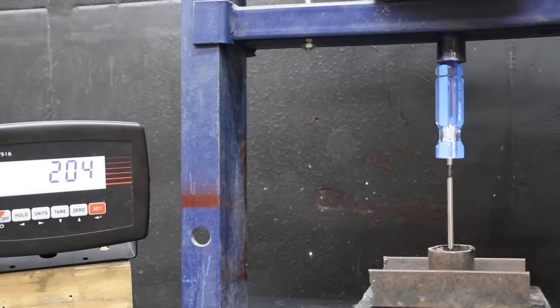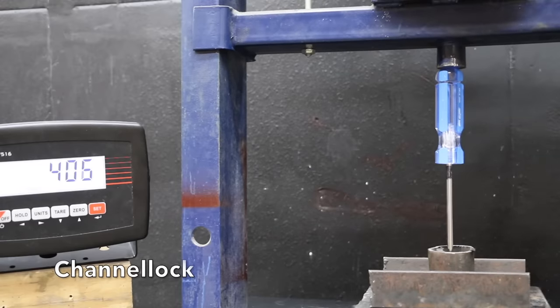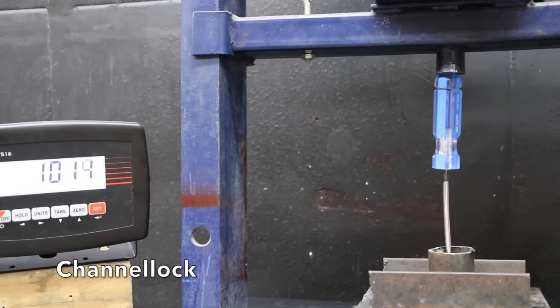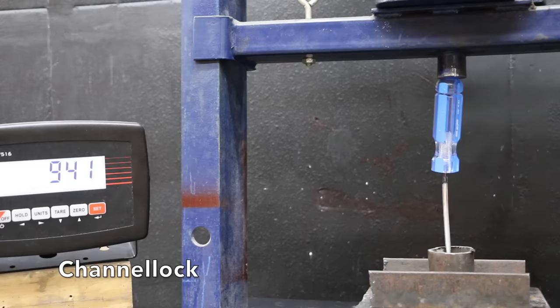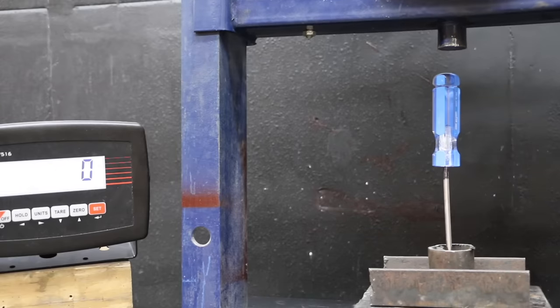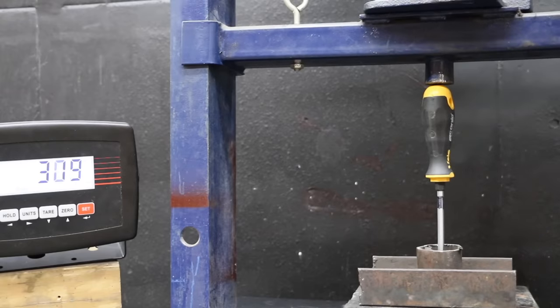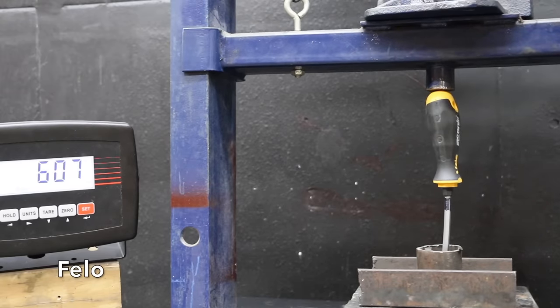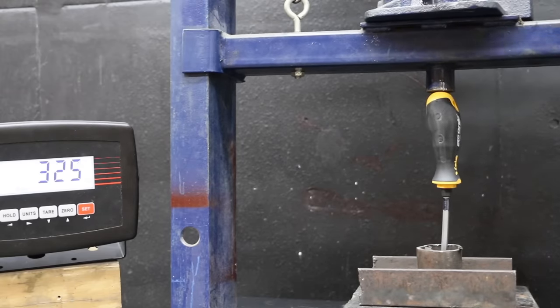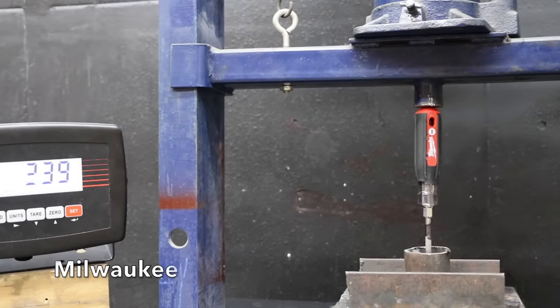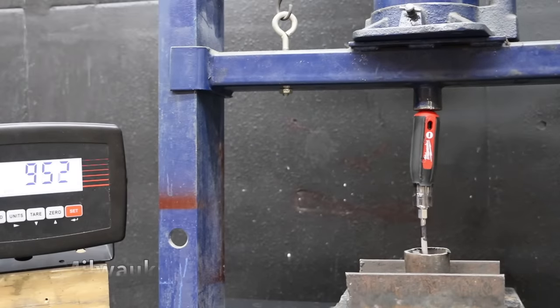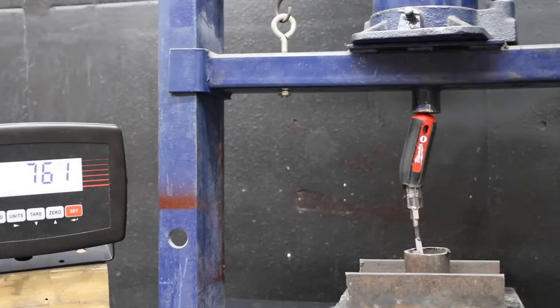Just like the Craftsman, the shaft started to move up into the handle at around 200 pounds, but it stopped moving after about an inch. The shaft began to bend at 1,000 pounds, so the Channellock brand is still in the lead. With 300 pounds of weight on the Felo screwdriver, the shaft began moving into the handle. The shaft began to bend at 600 pounds. And the shaft on the Milwaukee stayed in the proper position during the entire test. The Milwaukee began bending at nearly 1,000 pounds.